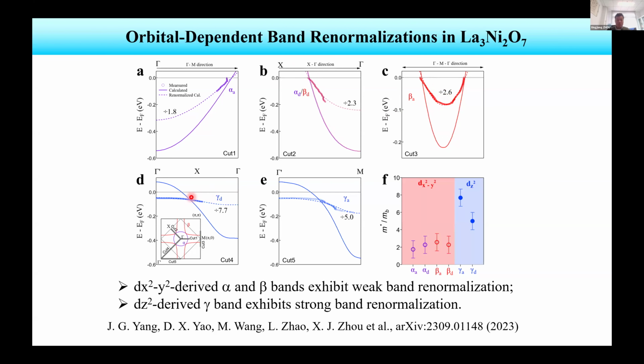And for the gamma bands, the calculated one without U crosses the Fermi level. It has a large bandwidth, but the measured bandwidth is much smaller. This is along the diagonal, and this is along the axis. So the measured bandwidth is much smaller. It's about 5 to 7 times renormalization.